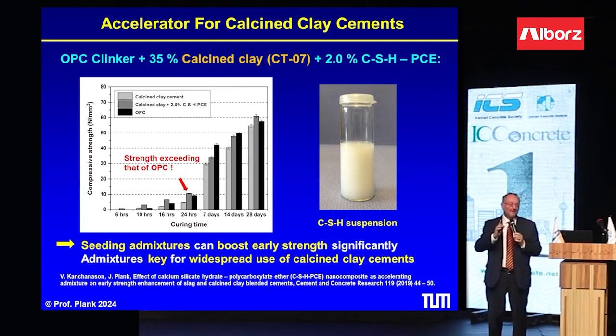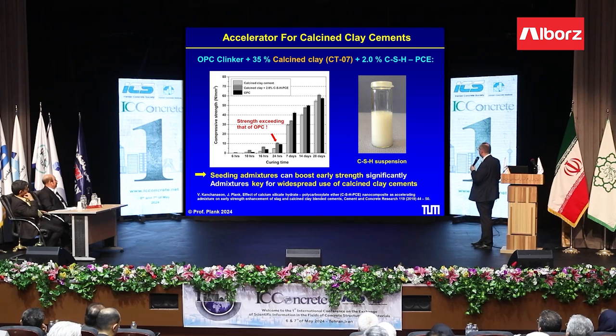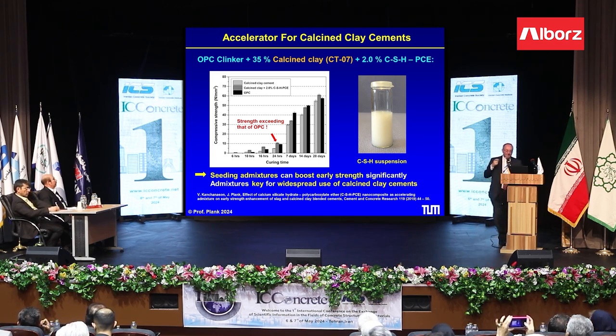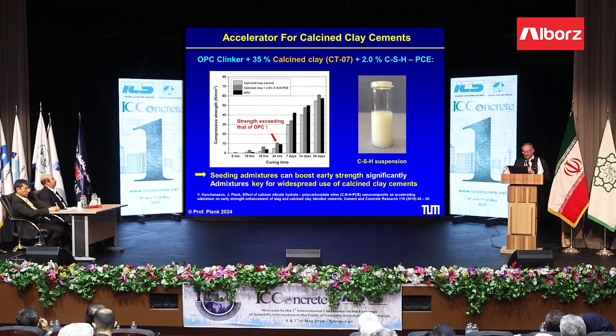The one-day strength is very important. The companies always want at least 10 megapascal after one day. And so we designed an accelerator, which is a CSH nanoparticle suspension. And as you can see on the data here, it gives more than 10 megapascal after one day, after 7 days, and so on. So with these admixture accelerators, we can solve this problem.